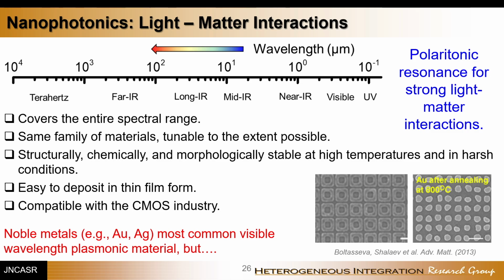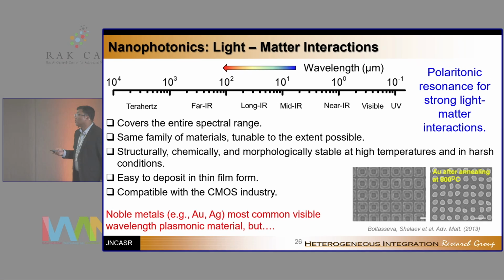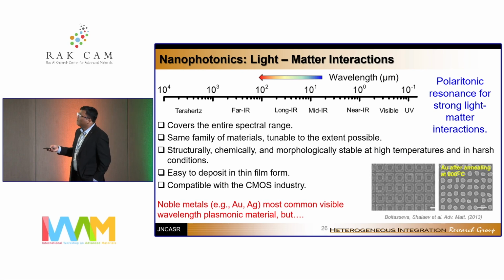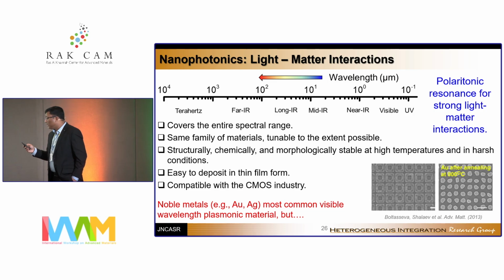But unfortunately, for practical application, gold and silver you cannot deposit in ultra-thin film form because they have a high surface energy. They basically aggregate. They are not stable at high temperature. You can't integrate them with CMOS technology. And that is why for practical application, you really can't use gold and silver.